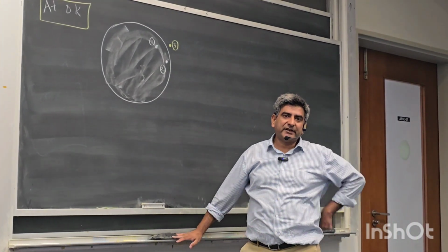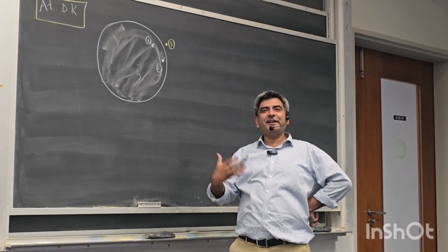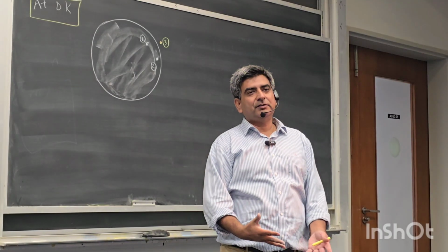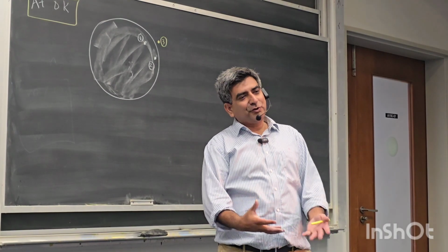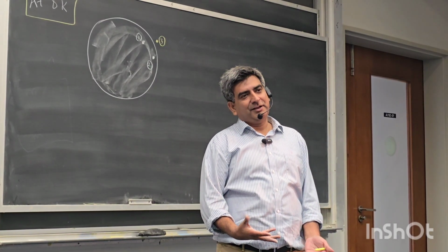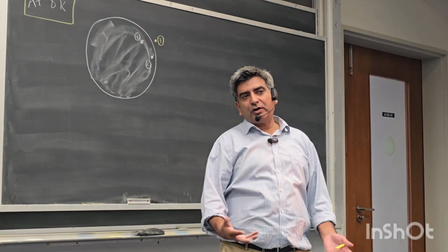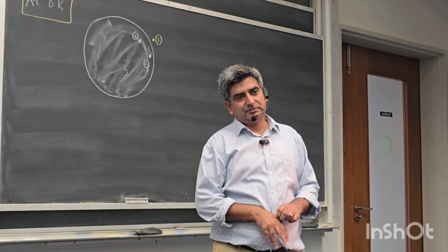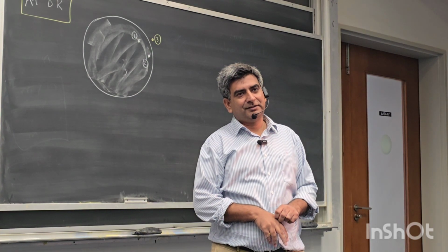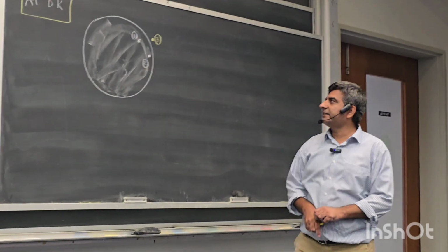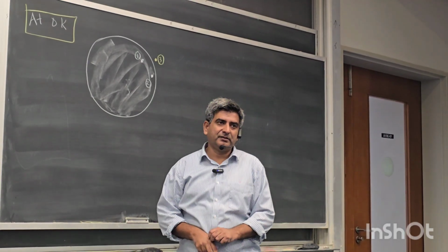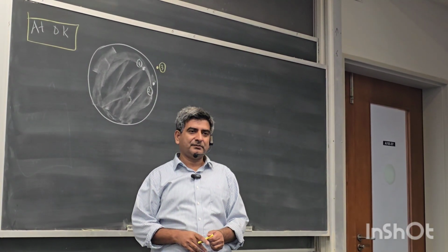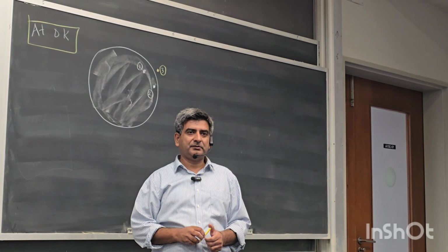Otherwise you won't be able to conserve energies. But nothing can be created inside the Fermi sphere because the parking lot is already full. So a fourth electron cannot be created, which means electron-electron scattering cannot take place at 0 Kelvin. It's forbidden. Electron-electron scattering is out of the question at 0 Kelvin because of the Fermi-Dirac statistics, the Pauli exclusion principle.